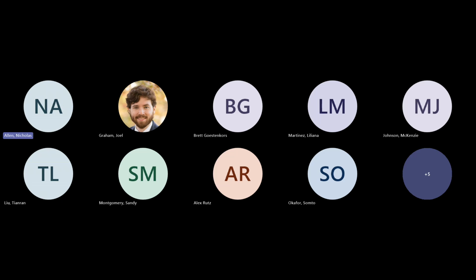I use thermal evaporation to fabricate custom gold electrodes. There are two sensing electrodes in the center, about 6 millimeters in diameter, and those are connected to contact pad electrodes at the end where we can use alligator clips to connect to the data acquisition system. I then deposited granular hydrogel deposits on the sensing electrodes and placed antennae into the granular hydrogels so that both ends are completely encapsulated by the material and still interfacing with the underlying traditional gold electrodes.